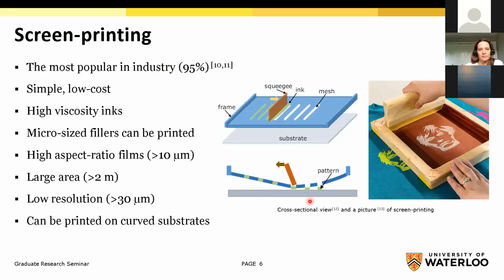So that ink has rheological, non-Newtonian properties. When you apply force to that highly viscous ink, the viscosity of the ink is reduced. With reduced viscosity, the ink flows from these openings and is deposited on the substrate. Otherwise it can stay here without sweeping the squeegee. That's why high viscosity inks are required for screen printing.